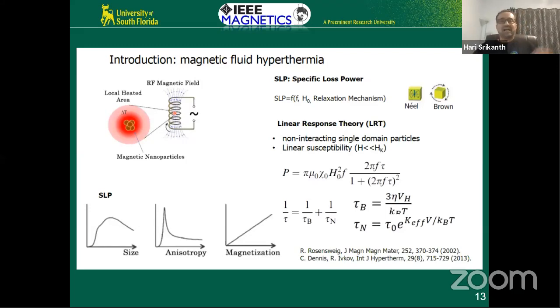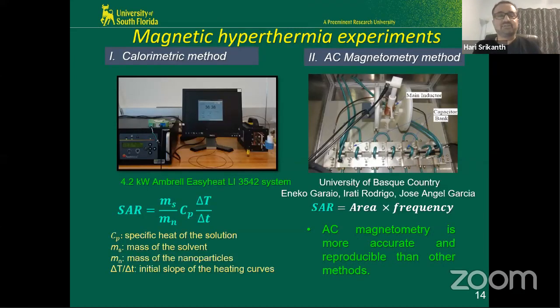Okay, now how do we measure the magnetic hyperthermia? All right. It turns out that we do two sets of experiments, one done in Florida in my lab at USF, and the second one we take the particles and send it to Spain to collaborators in the Basque Country in Bilbao, and we measure the same SAR. This is the same figure of merit done using calorimetry. In this case, we have an AC power supply. The particles are inside an inductive coil, and then we apply an AC frequency, and we have a thermometer here, right? A temperature sensor, and we can actually measure the rate at which the temperature increases.